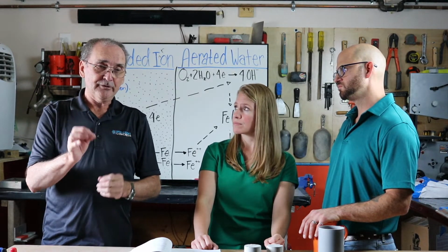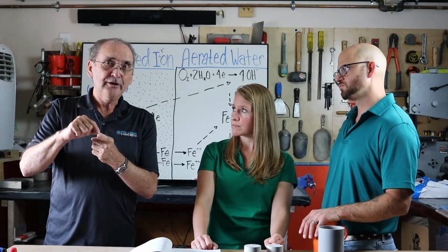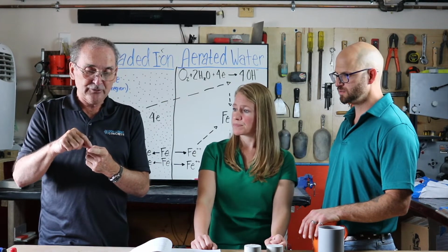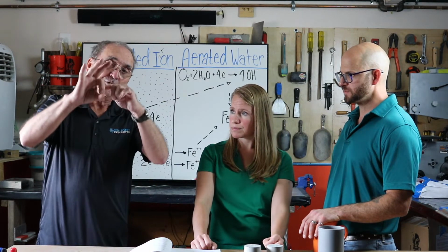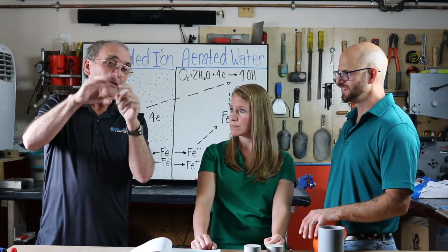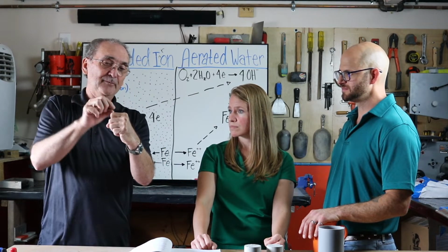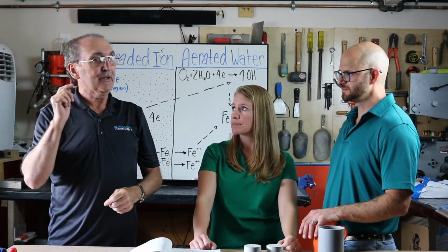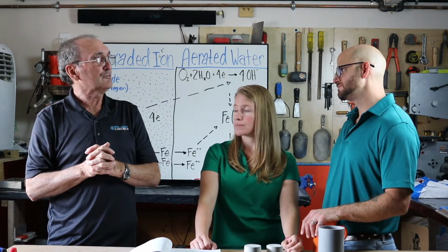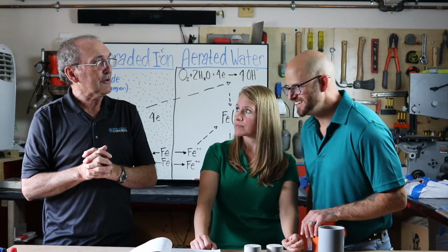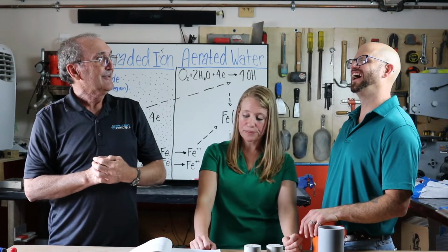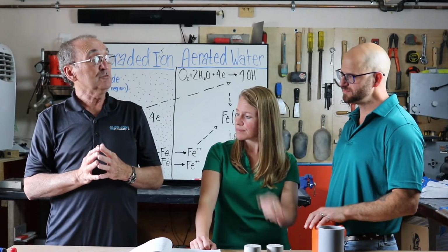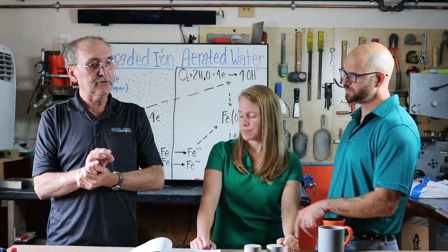Because in pre-stressed concrete, we get a little pit of corrosion, and it causes stress intensity. Oh my gosh. So that singularity, that one little spot, all of a sudden, when it had this nice uniform stress on it, now it doesn't. Now it's got this one spot where the area gets smaller, causes stress intensity, and when that piece of steel breaks, it sounds like a .22 rifle. It does. You can actually hear it. It goes ping when it breaks. Wow. And so in pre-stress and post-tension, the problem's even worse because that first little spot of corrosion causes that stress intensity.